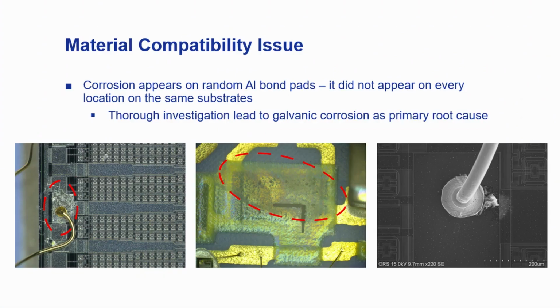So talking about customer case studies, I would like to mention a military and aerospace customer who are mainly focusing on power electronics. They were manufacturing DCBs and IGBTs, where there was an gold wire bonded to the aluminum pads. In this case, when we used an alkaline cleaning agent with improper corrosion inhibitors, we found that the aluminum pads were reacting and forming a white residue corrosion, which was due to the impact of galvanic corrosion.